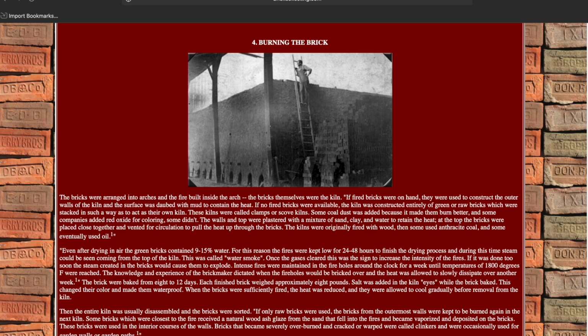Imagine that, guys, steam called water smoke. How fitting. Once the gas is cleared, this was a sign to increase the intensity of the fires. If it was done too soon, the steam created in the bricks would cause them to explode. Intense fires were maintained in the fire holes around the clock for a week until temperatures of 1800 degrees Fahrenheit were reached. The knowledge and experience of the brickmaker dictated when the fire holes would be bricked over, and the heat was allowed to slowly dissipate over another week.